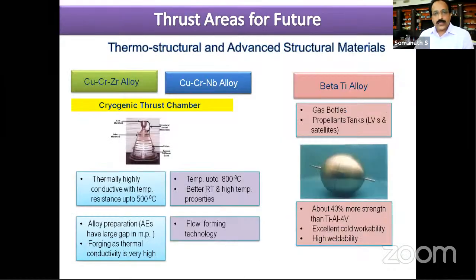In the thermostructural area, again, for a cryogenic engine, currently the material temperature limits are only up to 500 degrees centigrade, and we would like to increase it to something like 800 through these alloy developments. Similarly, for titanium alloys, beta titanium alloy development for gas bottles can bring in significant weight saving and also high processability for these alloys for tank manufacturing.